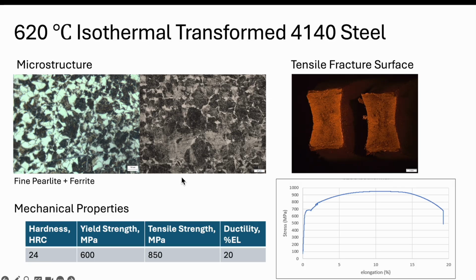And if we look at the tensile fracture surfaces, same thing. We see a continuation where we continue to see a change in shape here as more and more plastic deformation occurs. You might also notice the area is smaller because there's more and more necking. So we see that as well. So this sample is actually this on the same scale. It's actually smaller because we have more ductility, more reduction in area.